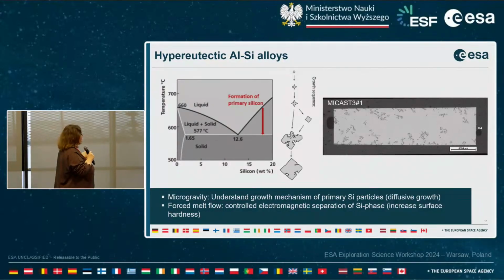And here you see a longitudinal section of MiCAST3#1, and you see, yes, with a rotating magnetic field, we are able to transport the primary silicon phase towards the outer part of the samples. So this is, in principle, a method to produce samples with higher surface hardness. But this is still under investigation, and of course, we are waiting for the remaining 4 samples.